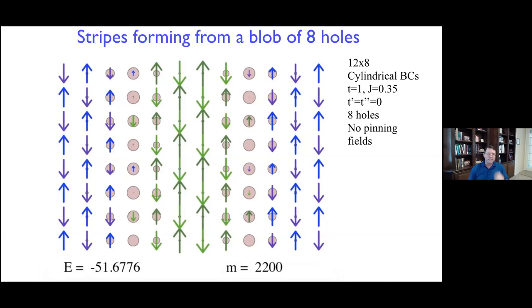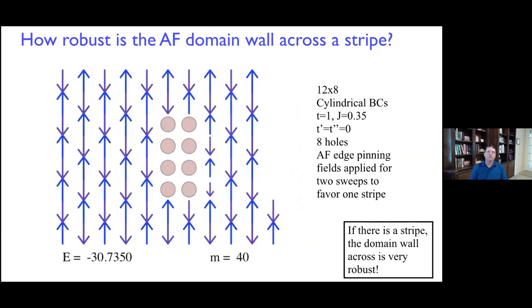What we see is that in between these two stripes, and this is an open cylinder, these two stripes have wrapped around. Each stripe acts like a domain wall, switching between the blue and the green phase. That's an essential part of what these things do. Now we can ask all sorts of questions about this and perform different numerical experiments.